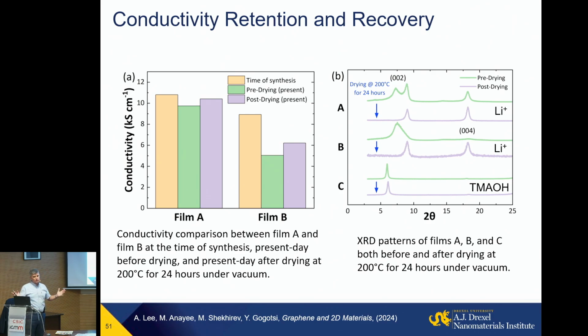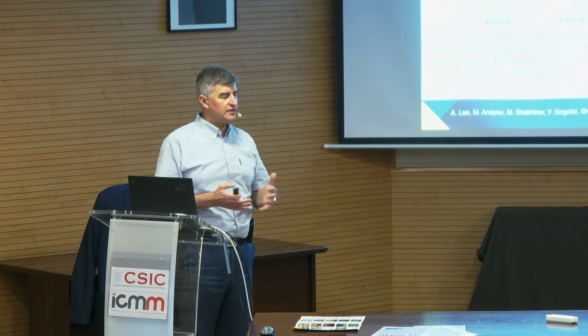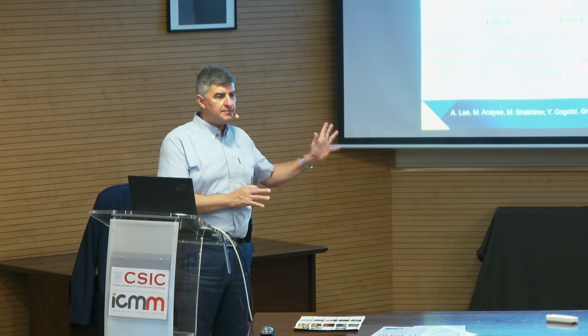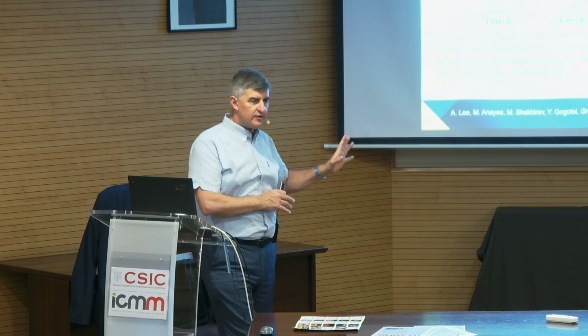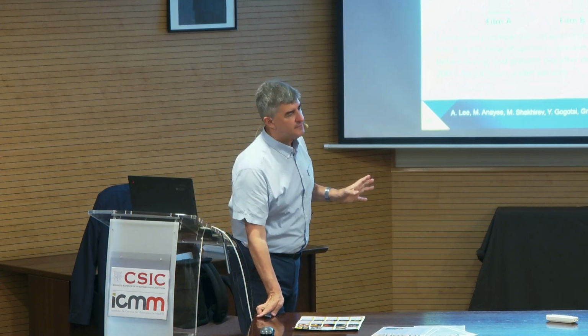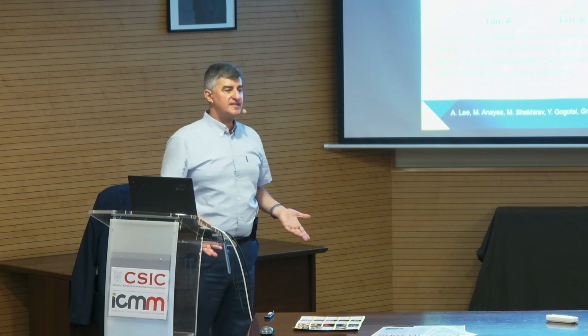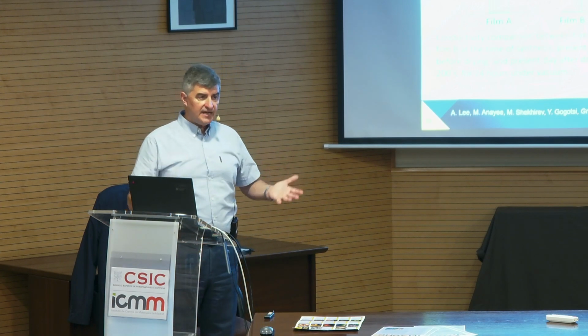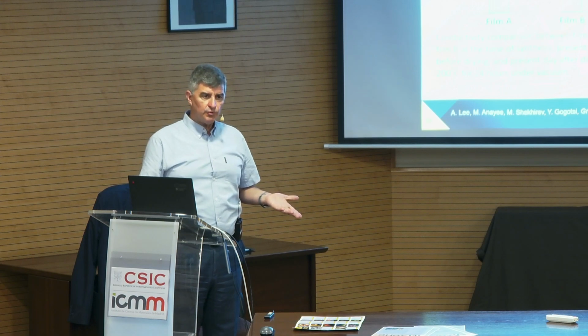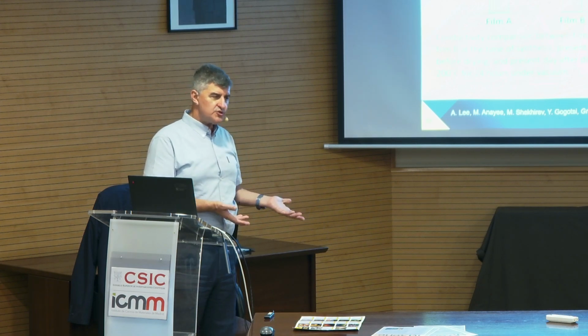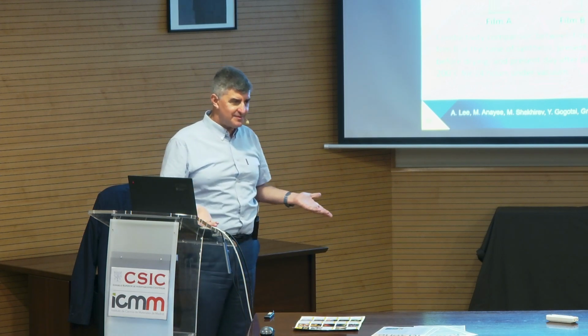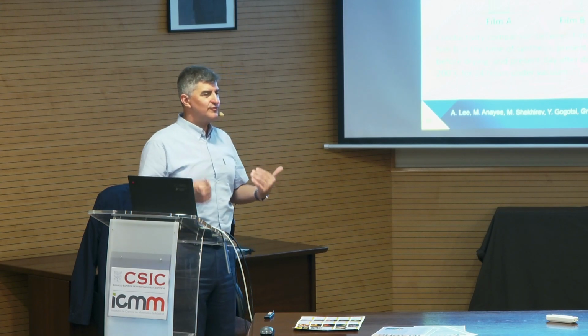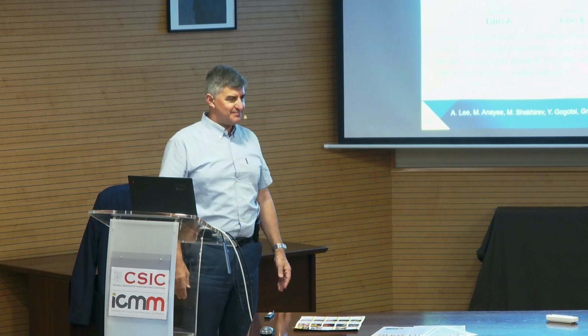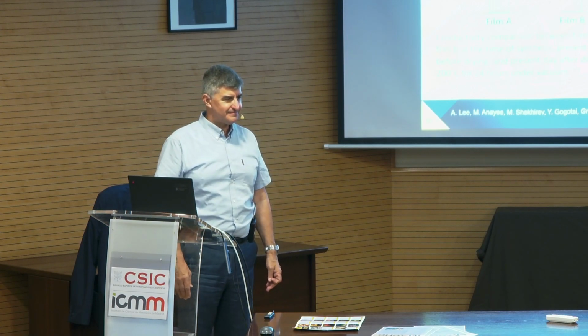All of them, we process in air, in water, in the lab. None of them is processed in a glove box or vacuum. So compared to the majority of materials used today, they're very stable. But there are limits. They can be transformed to oxide hydroxides, the transition metal carbides and nitrides. Thermodynamics is here, so we use kinetics to slow the process down.